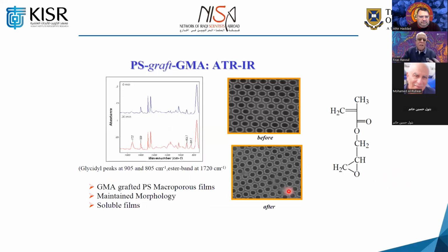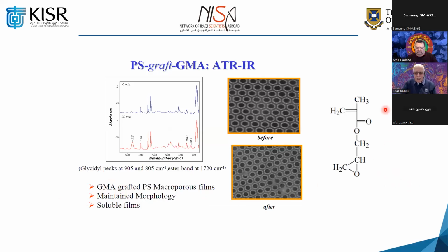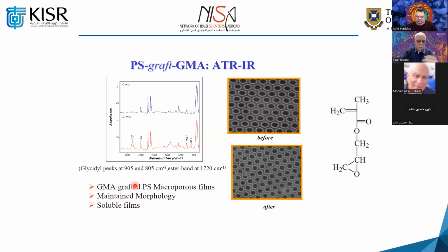How did we use it? We prepared a grafted surface of polystyrene, as I showed you before, and then functionalized it with glycidyl methacrylate, as you see. So sorry, it's a copolymer between polystyrene and glycidyl methacrylate. It's copolymerized. It's a graft copolymer. Then it was cast on a surface. We evaporate and we form that honeycomb structure.